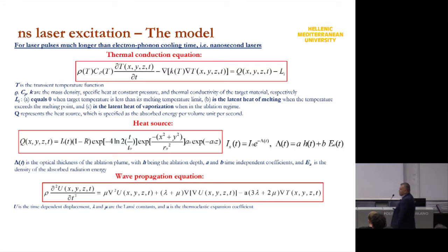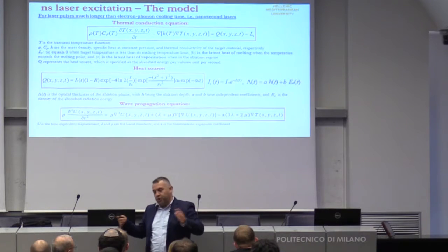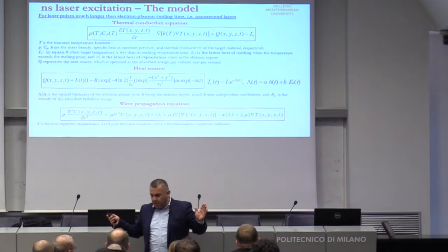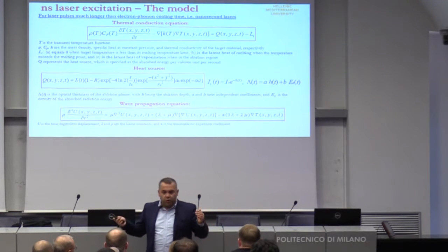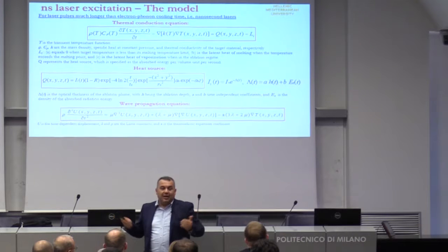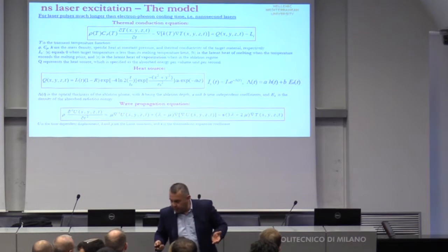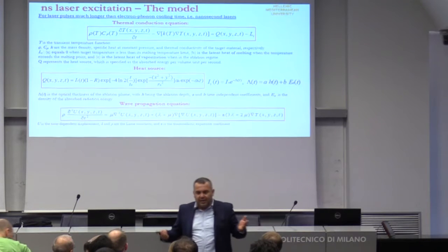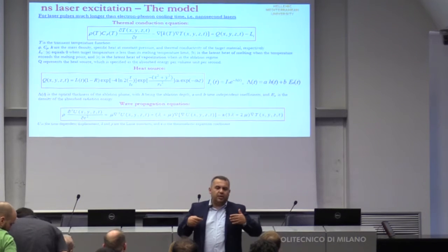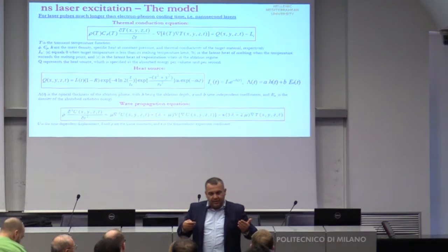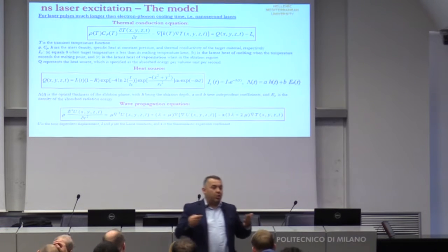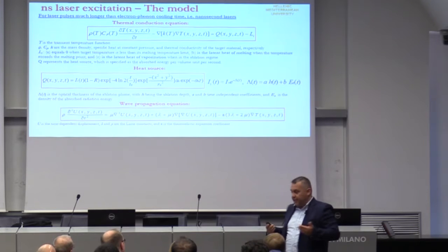Now, let's limit ourselves to nanosecond laser pulses. Why nanosecond? In nanosecond pulses, there is no difference between electron and phonon temperatures, because the electron-phonon interaction time is on the order of picoseconds. So when we have a nanosecond pulse, everything is already equilibrated. So actually, we can study only the bulk, only the ions, not the electrons.